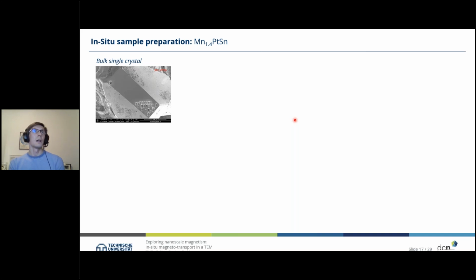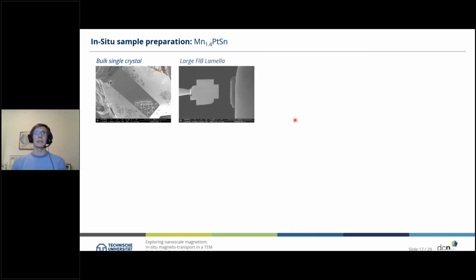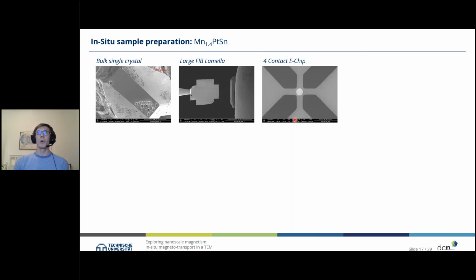But first I want to explain to you how we prepared the sample here, since this is a bulk single crystal, and we cannot sputter deposit such a material and then do the lithography. Instead, we need to cut out small pieces, lamellas, out of that bulk single crystal, where then we have a large FIB lamella, which needs to be very homogeneous and especially with the same thickness, if possible, and very low thickness of 100 to 150 nanometers over the whole lamella. Then we place this onto the commercially available 4-contact E-chip, where we cut in a small hole in the center.